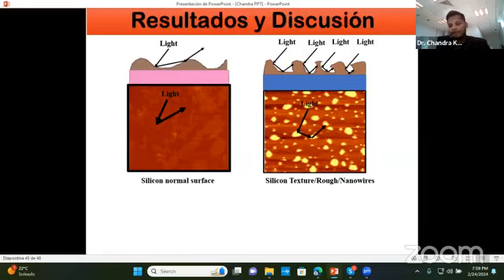Later we are working towards replacing that passivation layer with another material that could be silicon nitride, SiNx, Si3N4, or Al2O3, or a mix of those materials, because the passivation layer is more important to enhance the current or potential in our device. See here, if we are taking this as our material, this is, for example, the emitter here and the contact here.